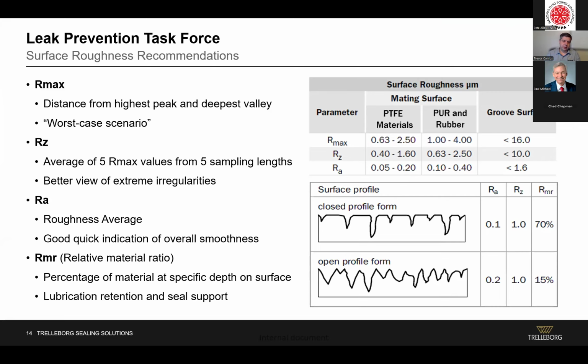So you can see in the picture there on the right, you have a closed profile form, which is preferred and recommended. We usually say 50 to 70% RMR is ideal. And that gives you good support for the seal. It's not riding along peaks, but you still have valleys to hold lubrication and lubricate the seal effectively. The picture on the very bottom right is an open form, we would say, and that has an RMR of 15%, as you can see, which is not ideal for the seal and is going to wear the seal much quicker than a closed profile form.